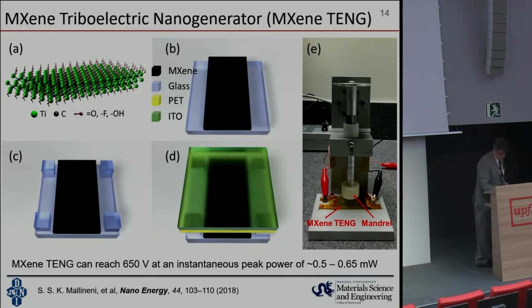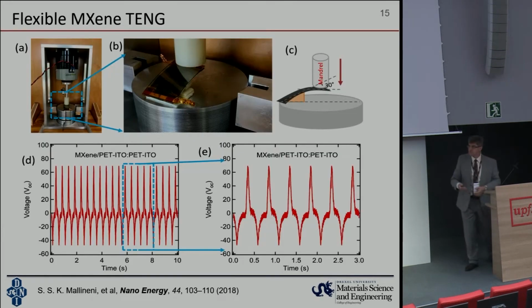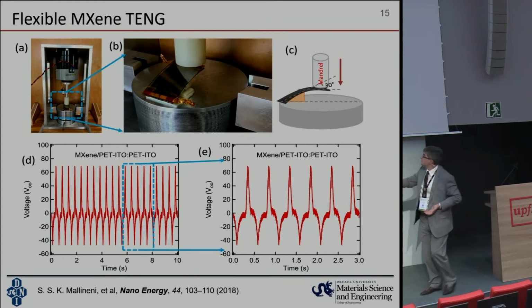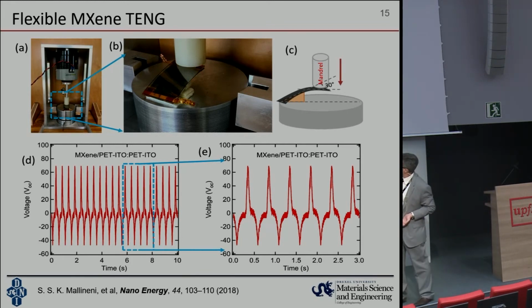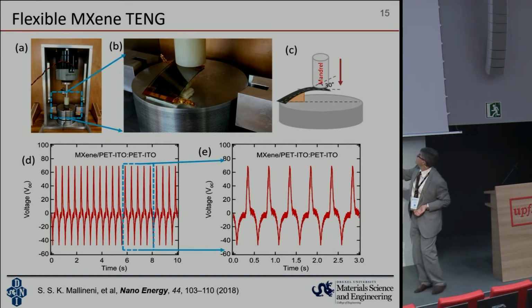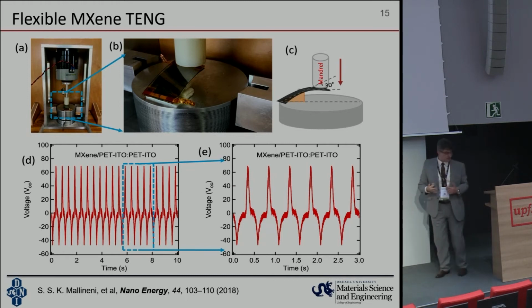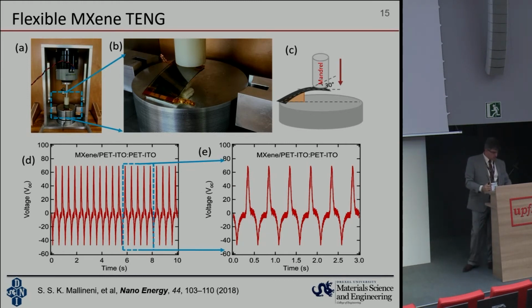So what happens if you do it with MXene films? You see a typical tribo effect here. Voltage is going to about 70, but actually we were able to push it about 10 times higher now. And you see the pulses of voltage produced from these contacts between the surfaces as you charge and discharge them here.